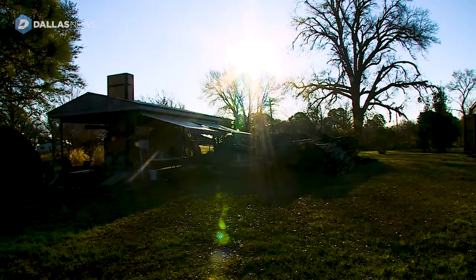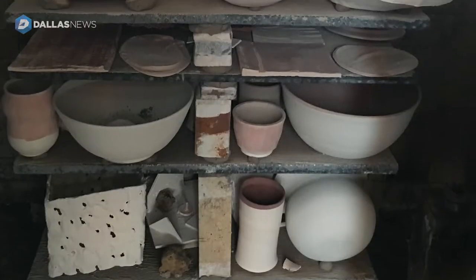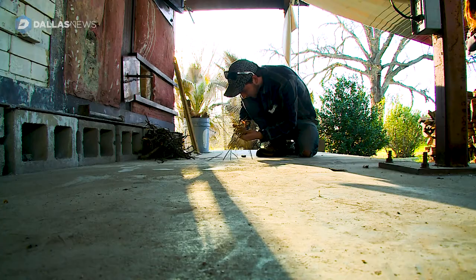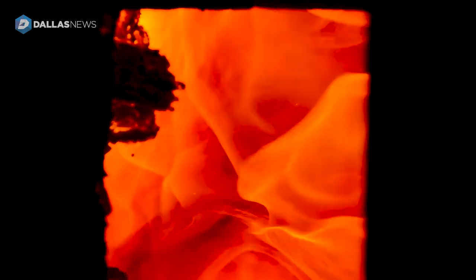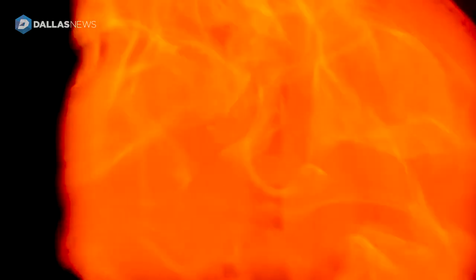We're on the west coast of Cedar Creek Lake at Louise Rosenfeld's Wood Kiln. We fire this kiln about twice a year, in the spring and in the fall. We start with a little campfire and build that up from twigs and dried grass, then move up to the second level of the firebox and start feeding it with bigger logs. We essentially keep feeding this kiln for about 26 to 28 hours on average, sometimes more. We want a steady climb of 100 to 200 degrees an hour until we reach 2200, 2300, maybe even 2400 degrees.